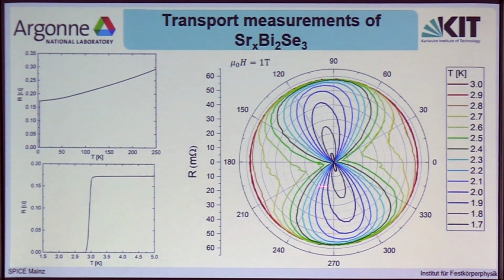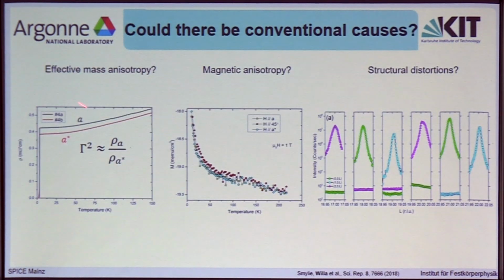Now, I promised you to exclude some of the conventional sources that could be at the origin of this. The ones we could come up with and that we've investigated is that you could think there might be some effective mass anisotropy in the plane. However, this would also show in resistivity, since the mass anisotropy can be related to the ratio of the resistivities along the 2 different crystallographic directions. We've done the measurements on one crystal, and you can see that there is not much difference between the 2 crystallographic directions. We actually attribute this more to a geometric normalization issue.